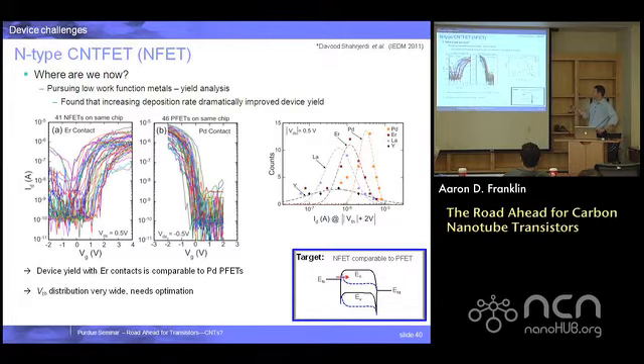You could see at the erbium devices here, the NFETs, the variation is a whole another topic, which we have some interesting insight into now, but it's a lot bigger than it is for the palladium devices. But the performance and the yield on a chip, when you spread the same density of nanotubes out and create the random devices, the yield for erbium contacted ones was very comparable.